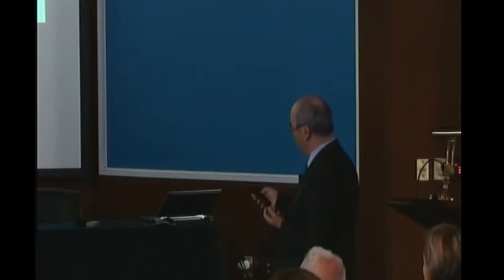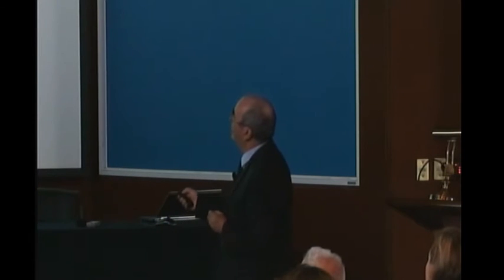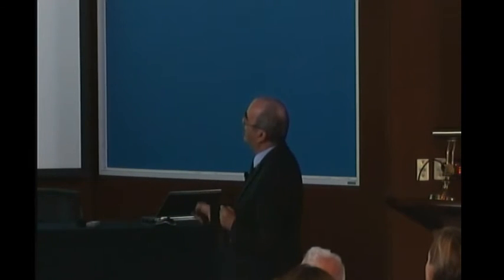And then, because of this volume change, we wanted to see if we can use it. The idea is the following. We made a bilayer like that. Here it's gold, as you see here. On it we can fix our spin crossover system. And then you have the bilayer system. When you have one layer which wants to change its volume, and the other one is fixed, then when you switch your system from one volume to the other one, you expect to have actuation.